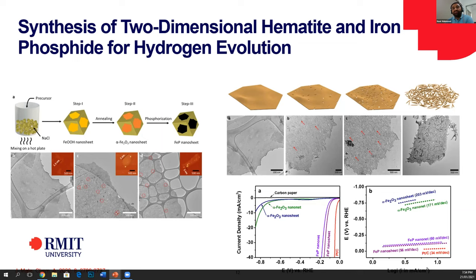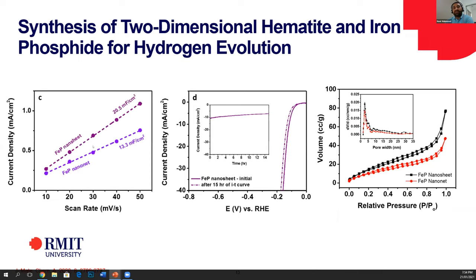But still we found that only disturbing the structure a lot, making disorders in the structure, is not the solution. So we did some further analysis, and we found that mainly the electrochemical active surface area is important. That is not only related to the surface area of the material, because sometimes we have more surface area, but the actual active sites are not exposed. So the main thing in material design is that we don't only need to develop a material which has a very large surface area, because sometimes they create many side reactions. We need the actual active sites to be exposed. So that told us that if we do such engineering, we can develop a better catalyst.